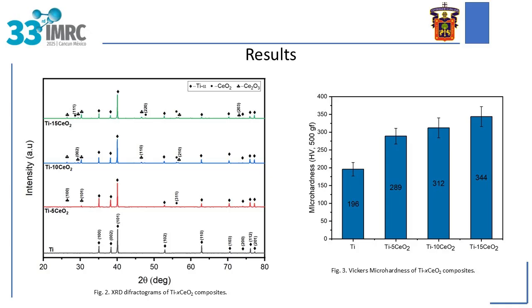The micro-hardness test demonstrated a steady rise as the ceria content of the titanium increased. The primary factors contributing to the hardening effect in the composites are likely the uniform distribution of ceria particles within the titanium matrix and the refinement of grains in the microstructure.